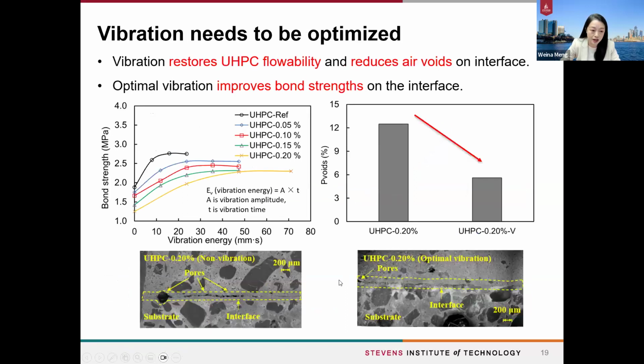So it is suggested that a little bit of vibration should be applied to the thixotropic UHPC in order to reduce the air voids and improve the bond strength. But for the vibration, we could optimize this process. We can use the minimum vibration time in order to achieve the acceptable bond strength, as the bond strength develops with the increase of vibration time, and it stabilizes after a while for different mixtures.